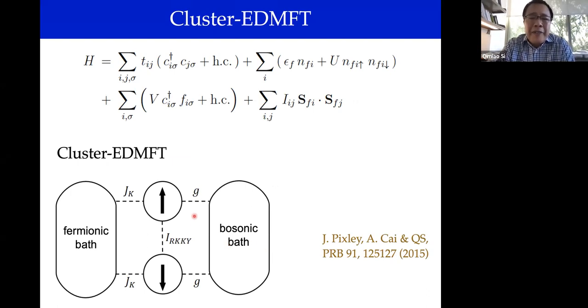But to actually theoretically describe it, we cannot just use the Bose-Fermi Kondo model, because if I have just a local moment, I cannot write down unconventional pairing functions. So we've extended the formalism to a cluster version, coupling at a minimum to local moments which are antiferromagnetically coupled with each other, and they are in turn coupled to the fermionic bath through the usual Kondo coupling, and also the bosonic bath through the feedback from the RKKY couplings with other local moments. So the equations are similar to what I wrote down earlier, but it shows up in a cluster form.